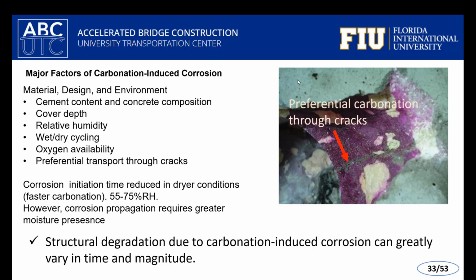Evidently, design is important, the cover depth. The larger the cover depth, the longer the path it takes for moisture or gases, including CO2, to penetrate through the system. So larger cover depth can buy you a little more time. Relative humidity of the environment is also very important because it's associated with how much water and moisture can be present within the pore system of the concrete itself.